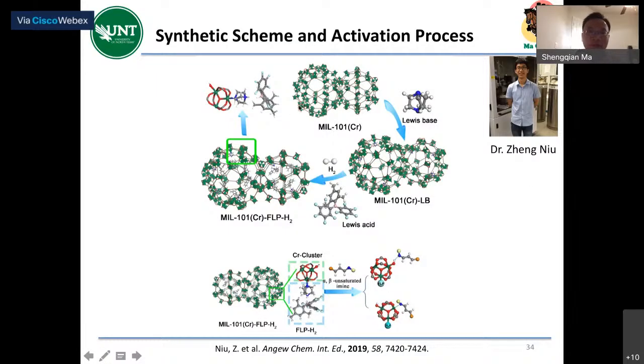Similarly, we also use the MIL-101, and the MIL-101 is a very good material. We can purposely keep some of the hydroxyl groups and also control the loading of the FLP and leave some open metal sites, because we know open metal sites can interact with nitrogen, and also the hydroxyl group can have hydrogen bonding with the imine group. So we leave this on purpose and use the FLP. This is different. We change the FLP, of course, and we want to use the hydrogen bonding hydroxyl group to interact with the imine bond to elongate this imine bond. Then we can use the open metal site to interact with the imine bond. So this imine bond will be activated. During the hydrogenation, this imine bond will be selectively reduced, but the carbon-carbon bond will stay.